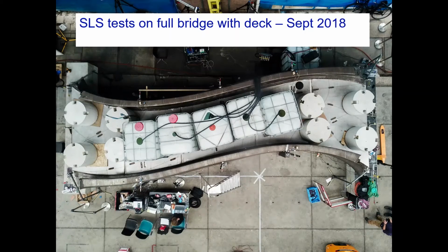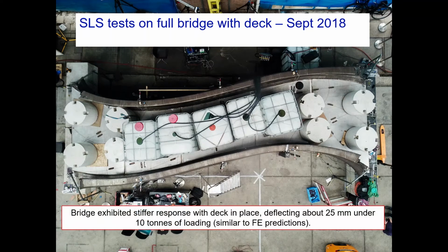So in the next step, the deck was welded in place. So this is a view from on top of the bridge, and you can see the continuous stainless steel deck there. And the total loading this time was applied up to about 10 tons, and it was through a combination of water tanks and concrete blocks. So 10 tons of loading, roughly corresponding to the serviceability design load on the structure, and the bridge deflected about 25 millimetres.